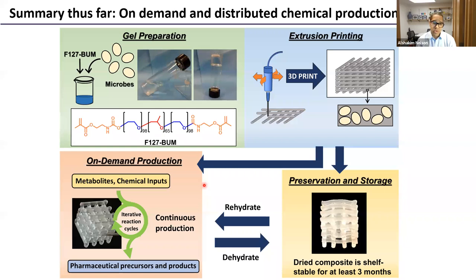So just to kind of summarize this first part, what we've demonstrated then is we have this F127BUM hydrogel that allows us to incorporate microbes. We can print that gel into different three-dimensional constructs and then either take that gel and preserve it in a dried state, and that dried state is stable for at least 3 months, or we can take it into the production state where we can use it for the continuous production of the desired product.